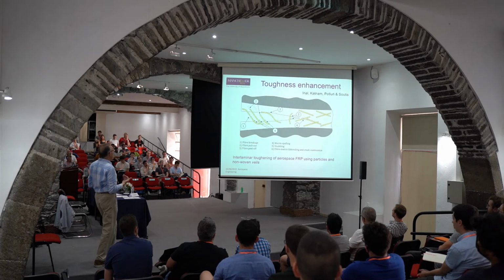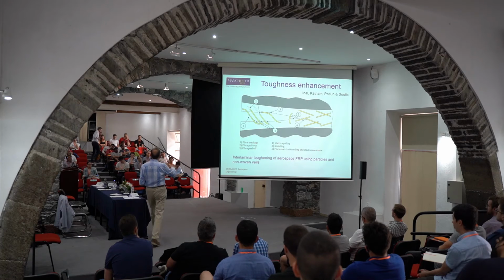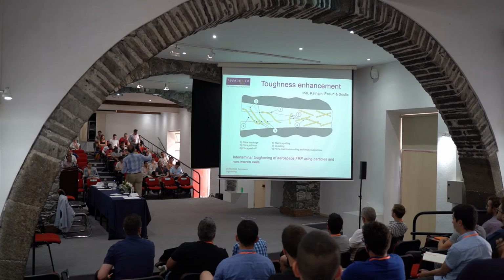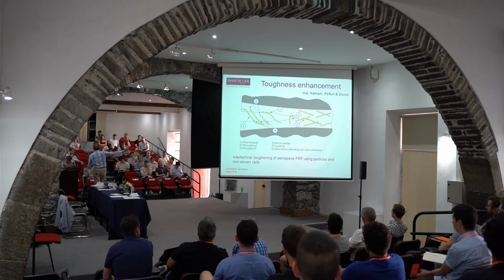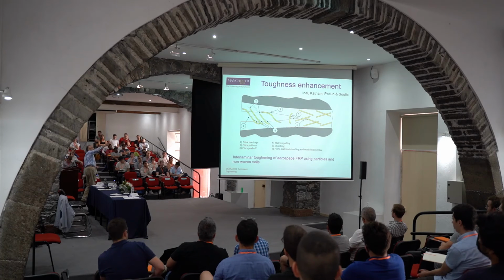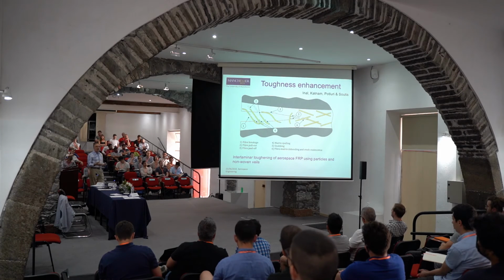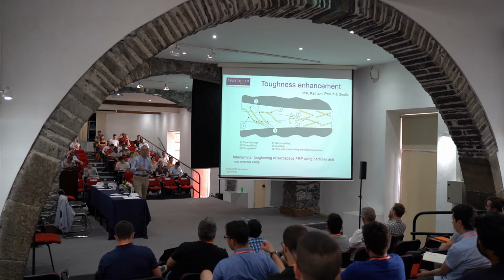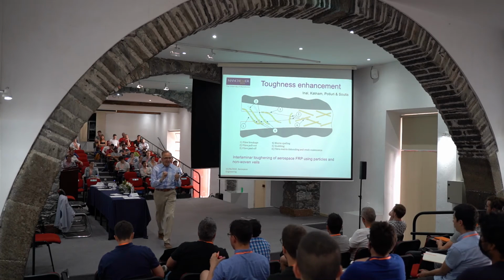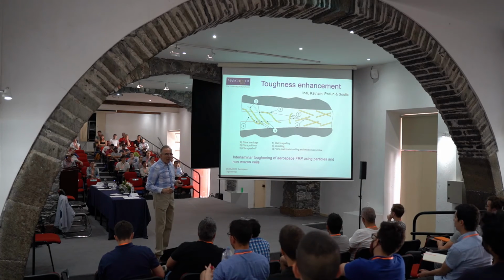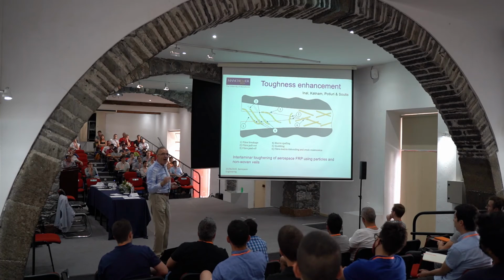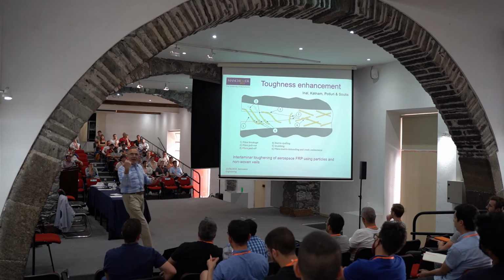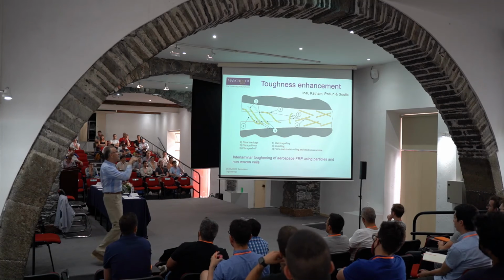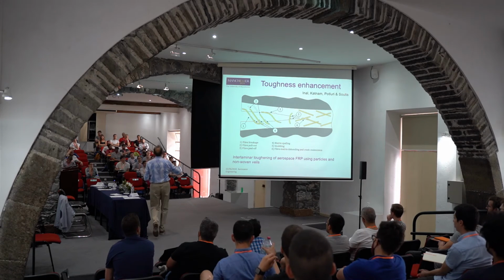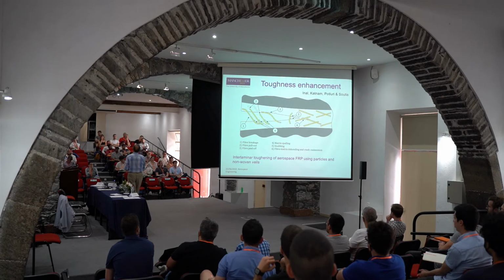And then another way is that when you get that crack, you have obstacles in front of the crack. And here we have small fibers, we have veils at the interfaces. So when the delamination initiates, it cannot propagate because its propagation gets prevented by those microfibers that we have inserted at the critical interfaces, which are estimated from our stress analysis, and they tell us that this is the interface that is going to delaminate. And this is where the stress analysis becomes so important.